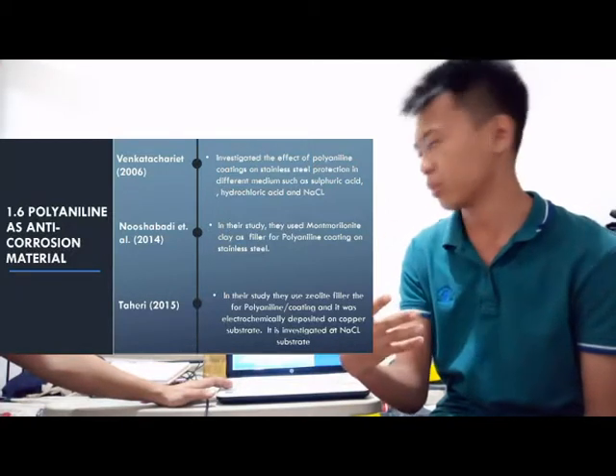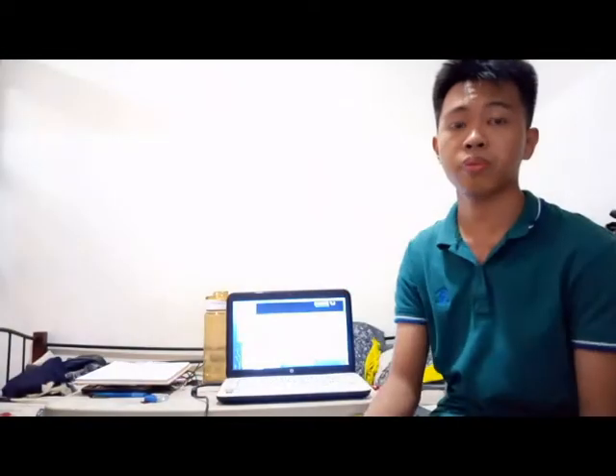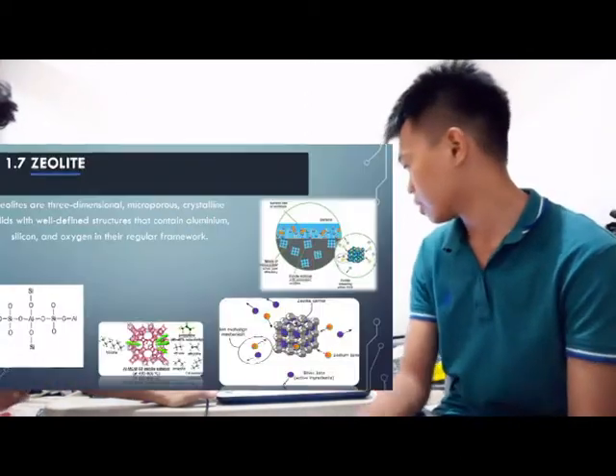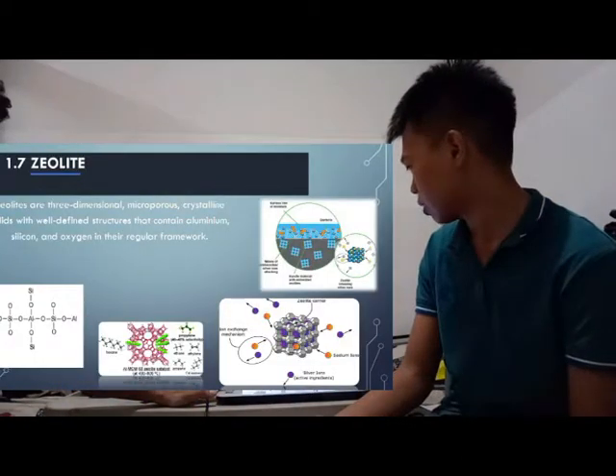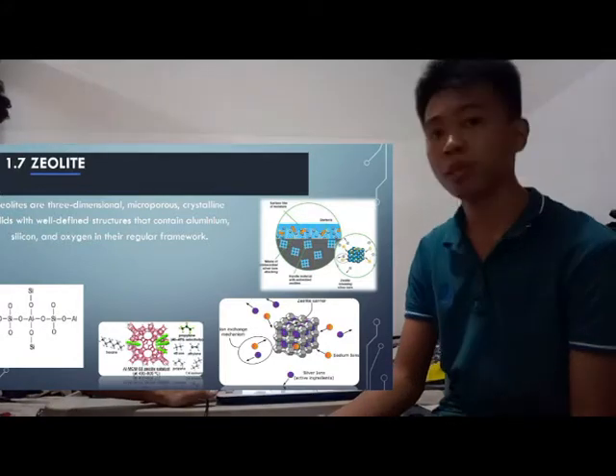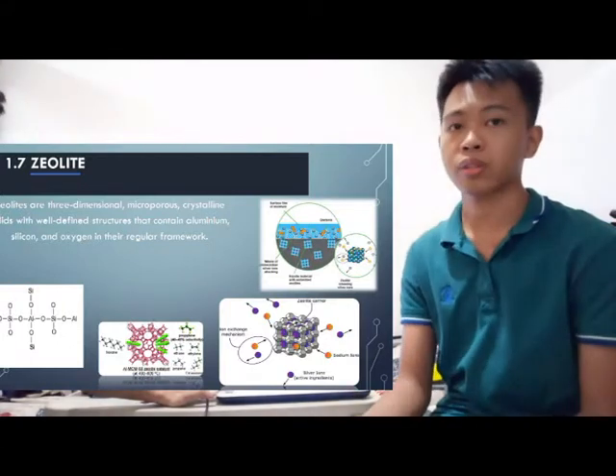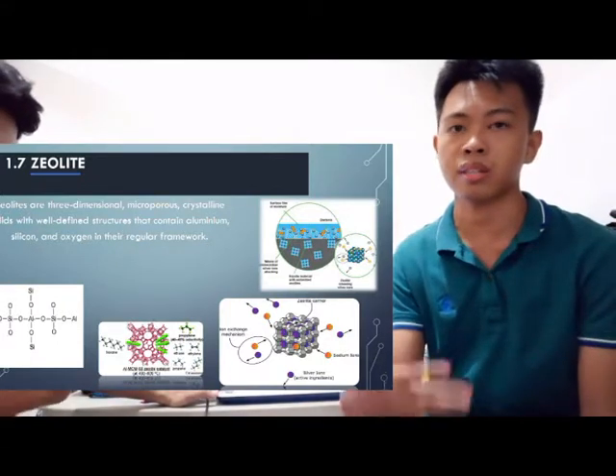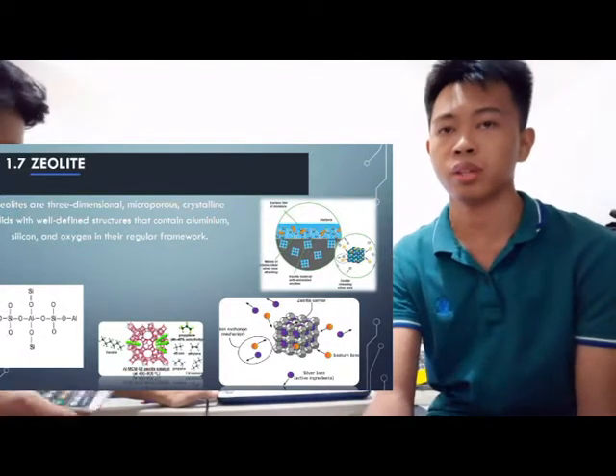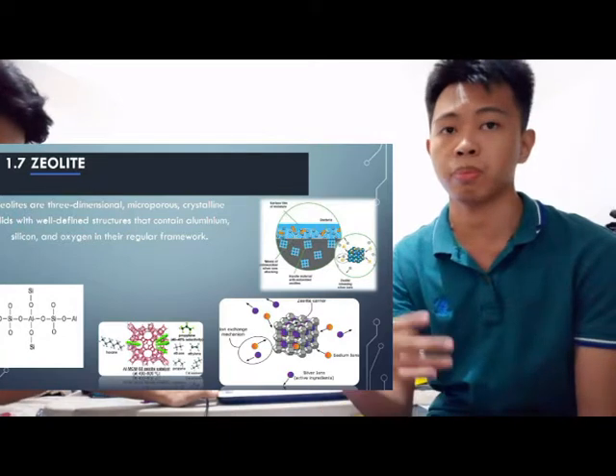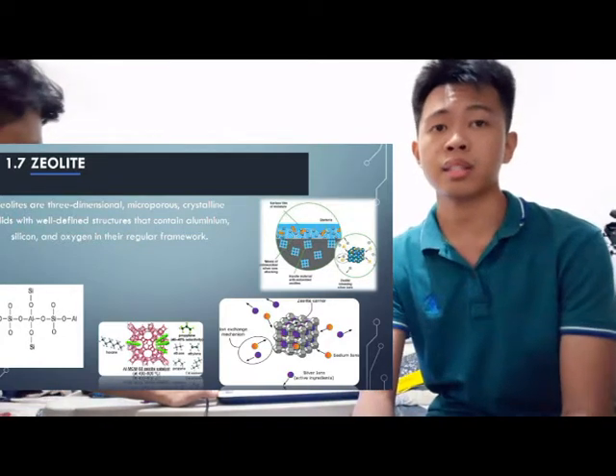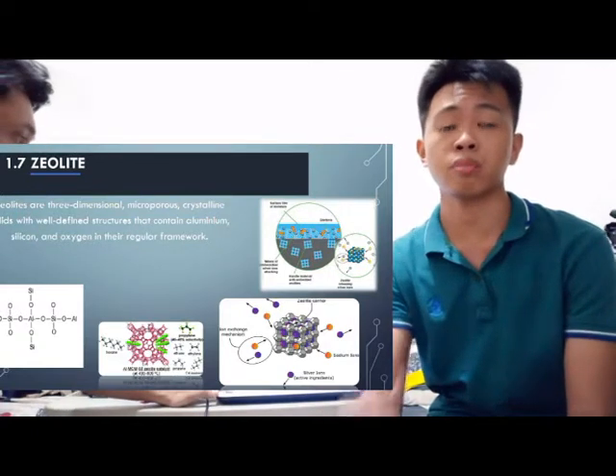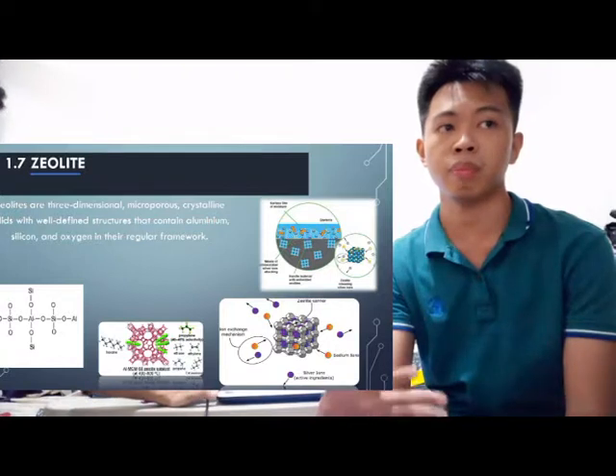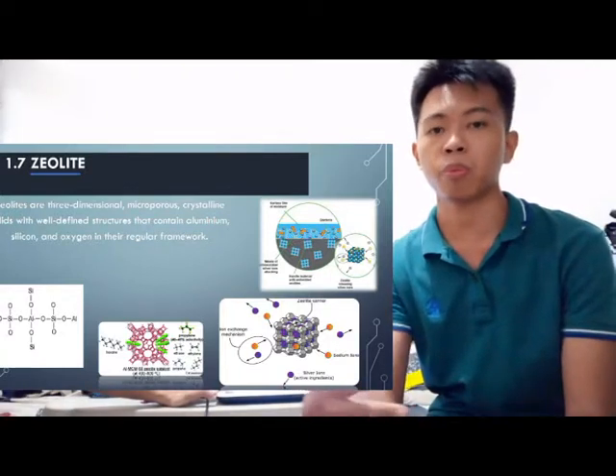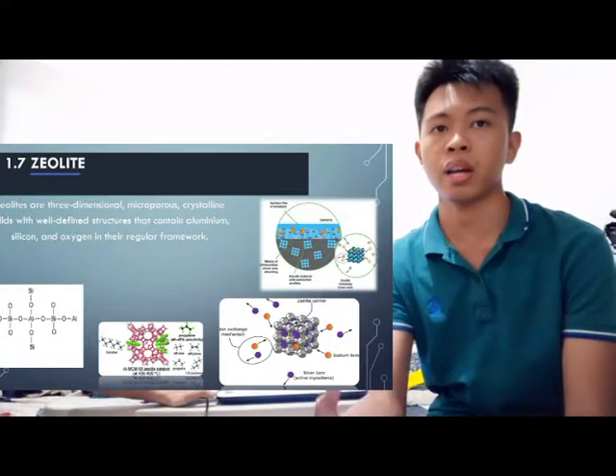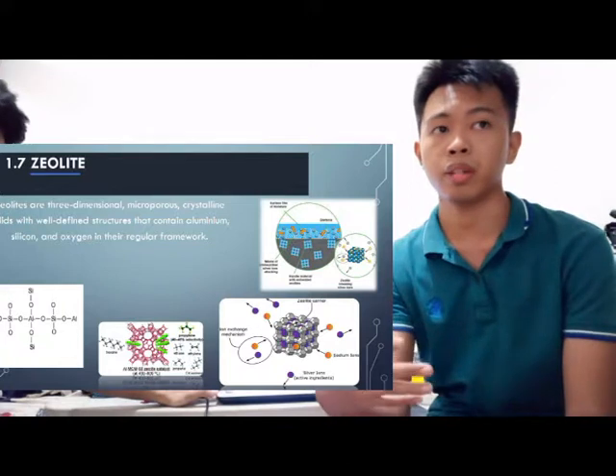So moving on, to give you a background of our filler, zeolites are three-dimensional microporous crystalline solids with a well-defined structure that contain aluminum, silicon, and oxygen in their framework. Generally, zeolites are used by many researchers as a catalyst, in ion absorption application, antibacterial application, and anti-corrosion application. The idea of zeolite as an anti-corrosion material is that zeolites are non-toxic materials. They are chemically stable and mechanically stable. In terms of its microporosity, it provides a high surface area and can enhance the absorptive property of the coating.